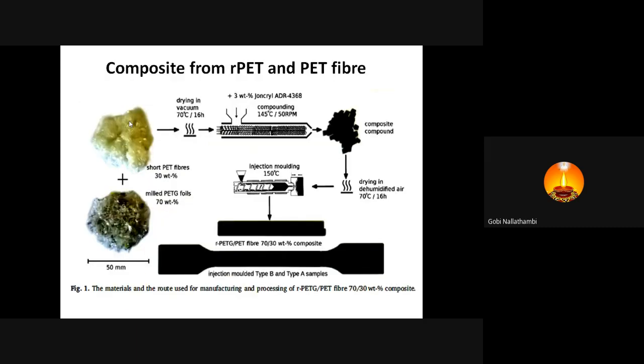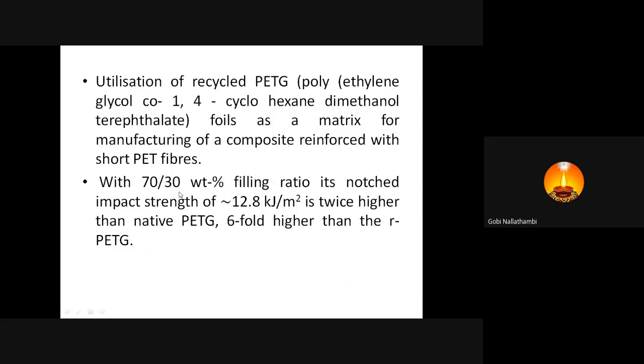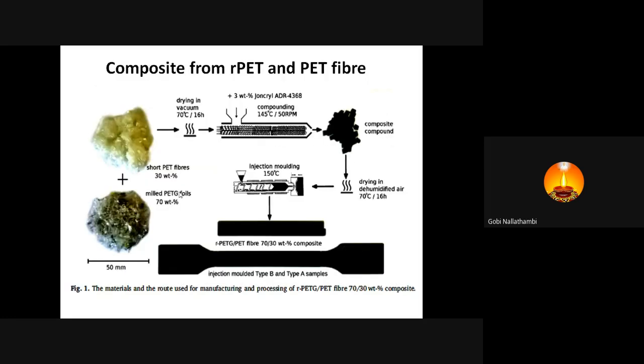So this is another composite manufactured from recycled material. There are short PET fibers. In this process they took 30% weight of PET fibers and 70% of PETG, milled PETG foils. PETG means polyethylene glycol co-1,4 cyclohexane dimethanol terephthalate. That foil is taken as a matrix for manufacturing a composite reinforced with the short PET fibers. So these two are mixed with different proportions.